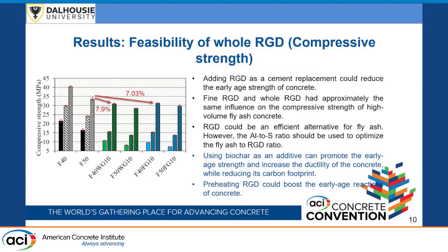So for the results, you can see that when we use recycled gypsum drywall, either as whole or fine particles, we receive almost the same results. If you compare the green one with the blue ones, we almost received the same results, which shows us the potential for whole recycled gypsum drywall instead of fine recycled gypsum drywall. We show that if we replace cement with recycled gypsum drywall, then the strength dropped. However, if we replace fly ash with the recycled gypsum drywall, the strength is not significantly affected. It just decreased by less than 10% at 90 days.